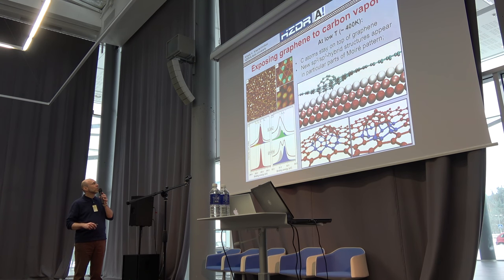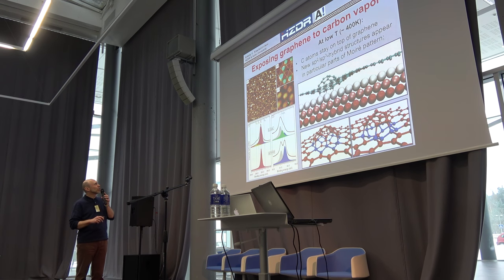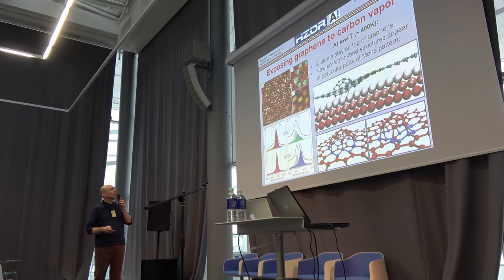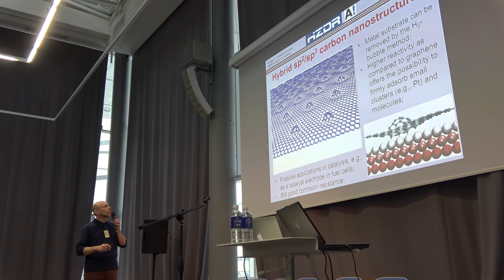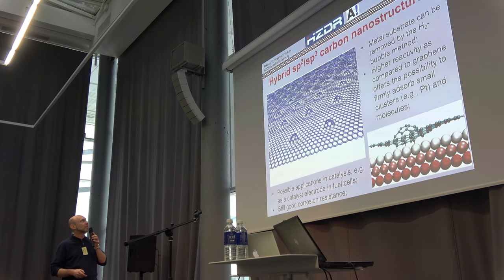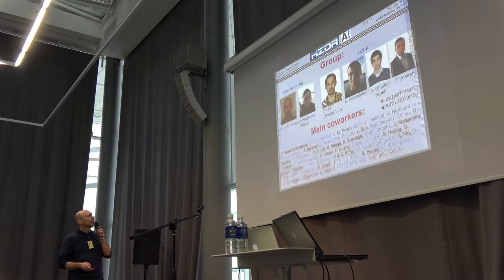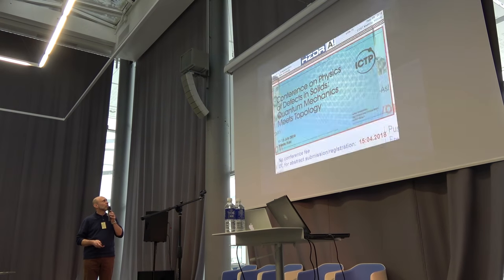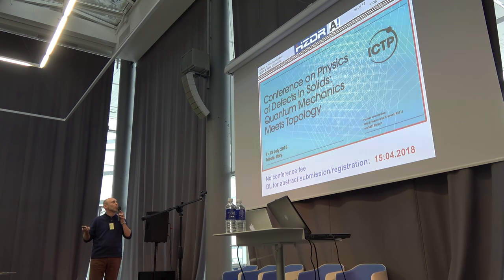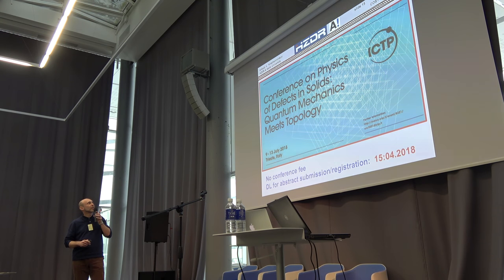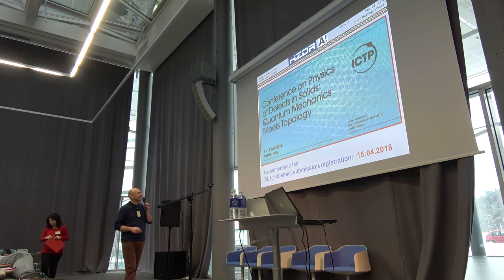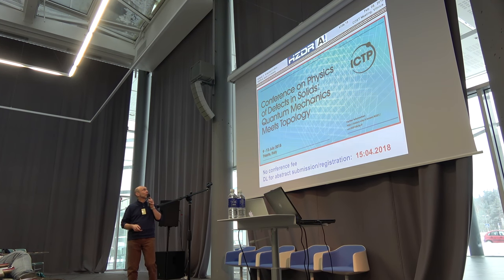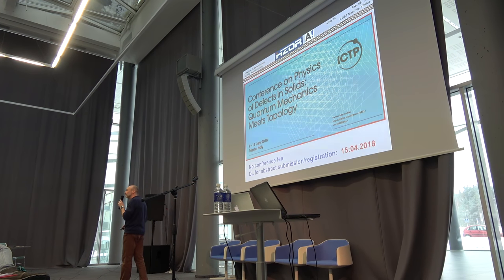At around 400 Kelvins, you get clusters on top with atomic resolution, and our calculations confirm this. XPS confirms that you have SP2 and SP3 hybridization in this area. Essentially what we see here are semi-caps of fullerenes. Moreover, you can remove the substrate and this material remains stable — it can be used for adsorbing individual metal atoms because these caps are naturally much more reactive. I would like to thank my group. We are organizing a conference in Trieste at ICTP in July — registration deadline is April 15th. Thank you for your attention.